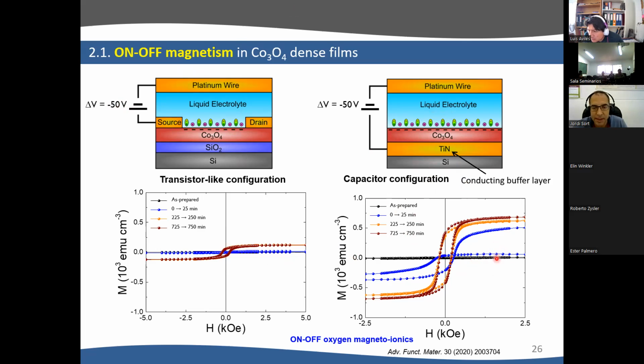So basically, these curves are consecutive hysteresis loops. The as-prepared is black. Then we apply minus 50 volt, if I remember well, yes, minus 50. Then the first loop is the blue one. So we start at saturation, there is no signal. And then as you are measuring the hysteresis loop, the magnetization is increasing. And this is why this first blue loop has this strange shape, and it's not closed. But after several loops, for example, between minutes 225 to 250, you can see that the loops are closed and we saturate the effect. And the same here, but you can see that the effects are much lower, basically.